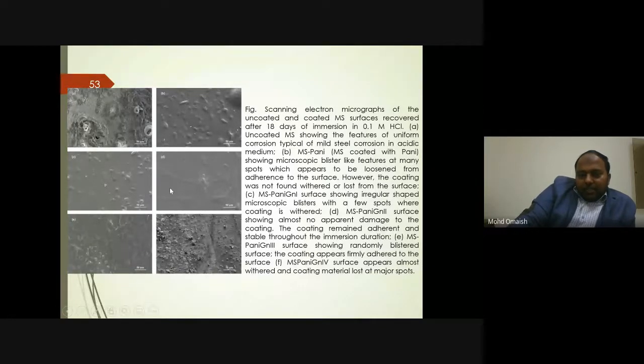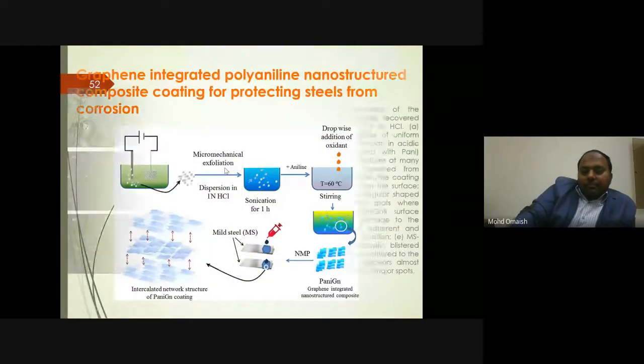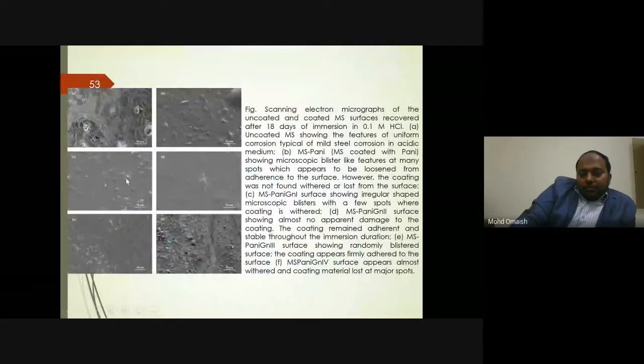corrosion is very less, but there has to be some optimum amount of graphene in the composite, because this is polyaniline graphene. Sorry, this is polyaniline graphene. There was some optimum amount of graphene, and at higher loading of graphene the results were not as good. So that's why the composite has to be optimized for corrosion. This is to show the application of polyaniline.